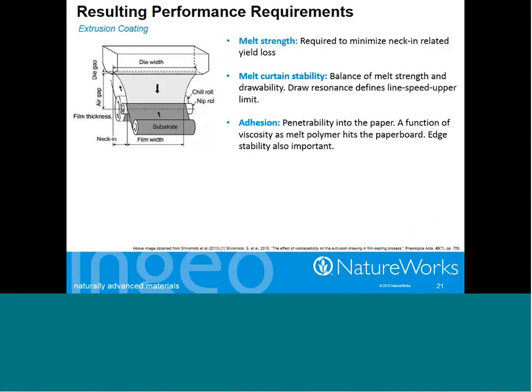Now, there are, as I mentioned, some performance requirements that have to be met in order to convince people to make the change, and those performance requirements are around melt strength and curtain stability of the melt, and some adhesive properties. So melt strength is important with respect to neck-in. So if you have poor melt strength, as you see here in the cartoon, what comes out of the die will get significantly narrower as it gets stretched and applied to the paper substrate. Melt curtain stability refers to what we would call edge weave. As you pull on that material coming out of the die faster and faster, you'll set up a resonance where the edge of the material will wander back and forth. If that's extreme, you'll end up with some yield loss, because the paper that gets used can only be as wide as the narrowest of the coated material.